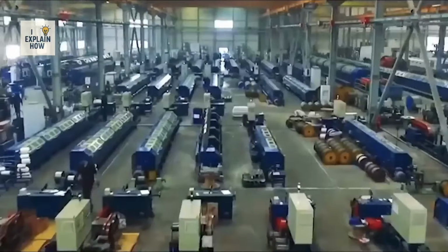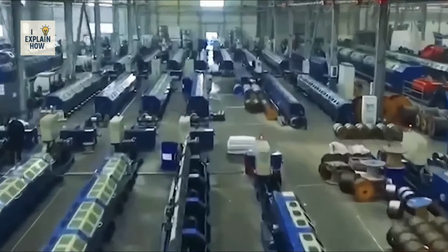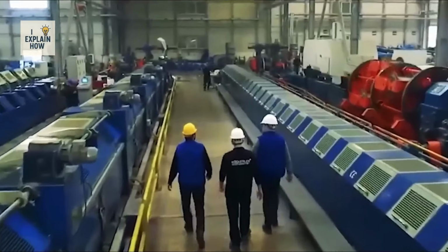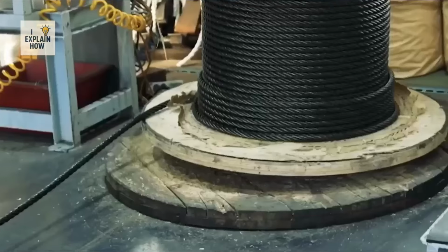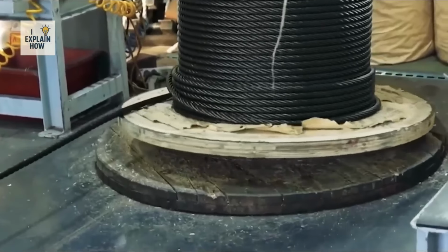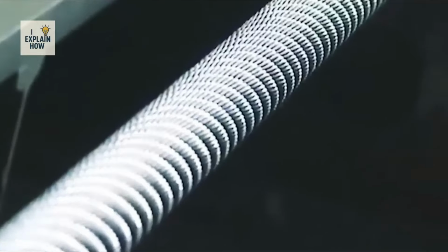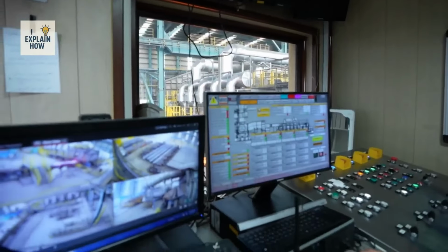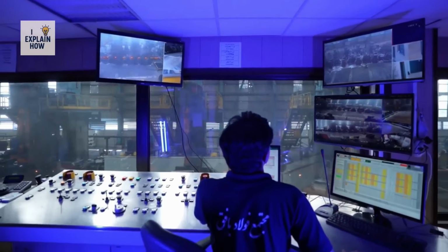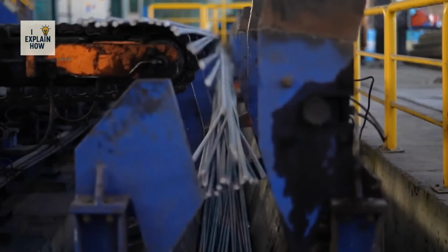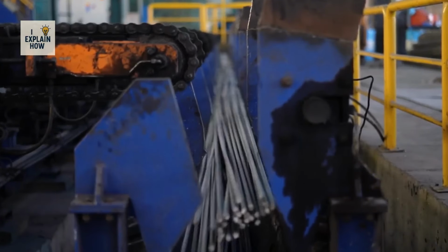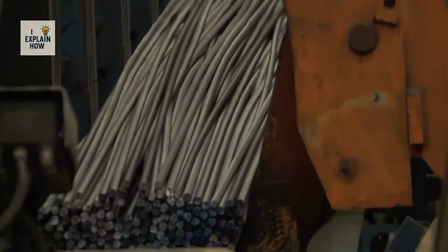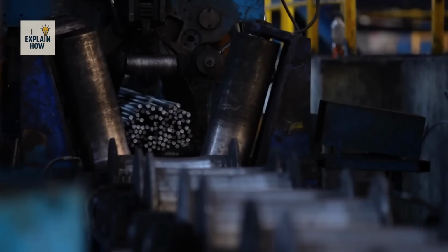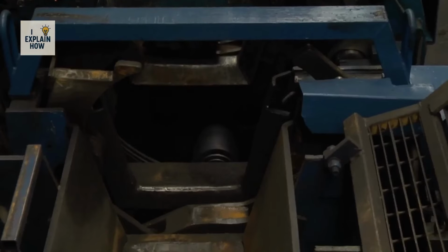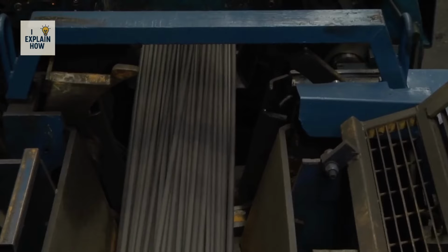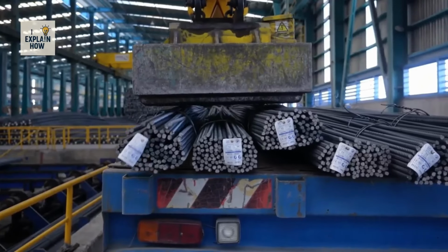This process, carried out at room temperature, requires careful control of tensile force, speed, and friction. Even the slightest variation can result in breakage or loss of ductility. In modern factories, laser sensors continuously measure wire diameter with automatic correction systems that adjust the tension in real time. The result is coils of steel wire with near-perfect precision, providing the strength essential for cable manufacturing. But achieving the right size is only half the battle.